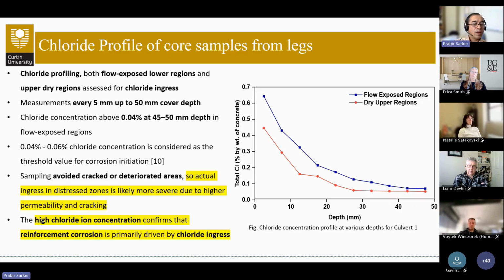So the high chloride ion concentration confirms that the reinforcement corrosion was the primary mechanism, primarily driven by chloride ingress.